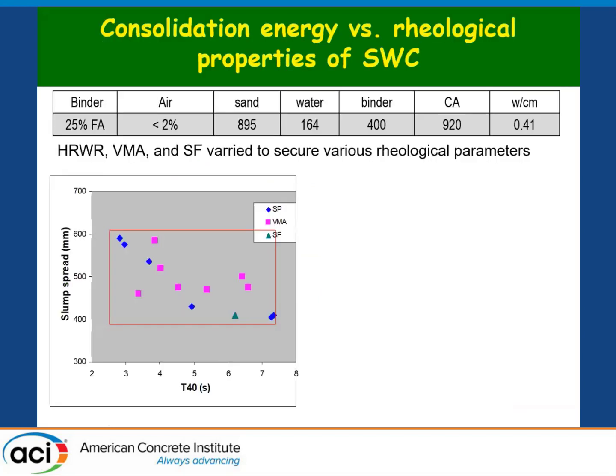So the question becomes, well, how much consolidation is enough? And is consolidation related to rheology? So we took here a typical SWC mixture. You can see that 400 kg per cubic meter of binder was 25% fly ash, with a relatively moderate water to binder ratio. And we changed the superplasticizer and the VMA, and in some cases silica fume, mainly to change the slump flow in the super workable consistency levels, so 500 plus or minus 100 millimeter.